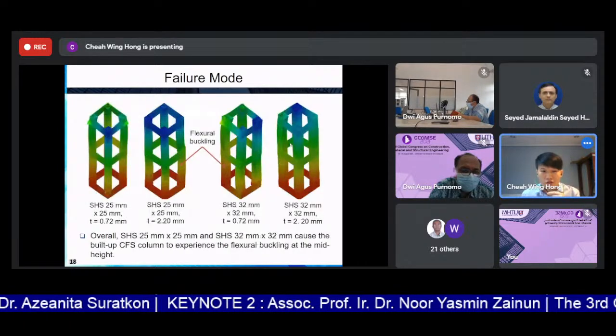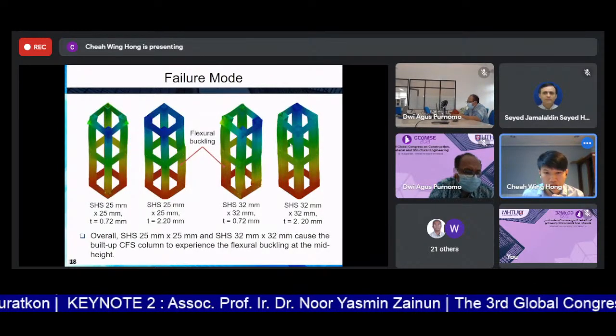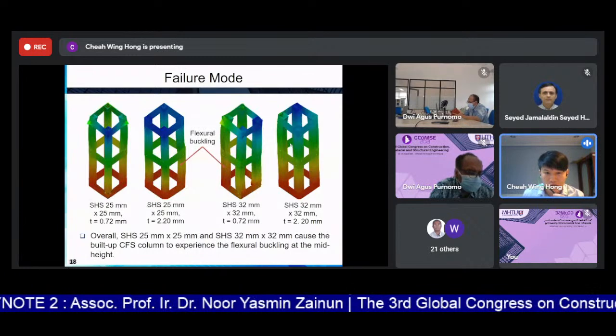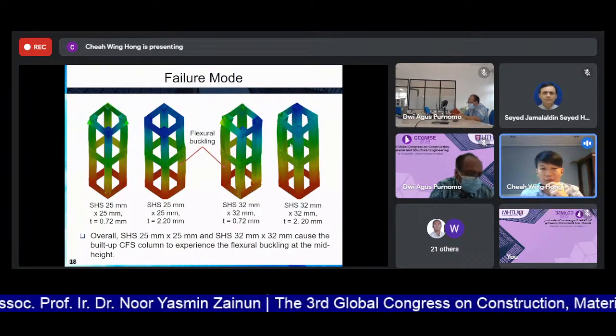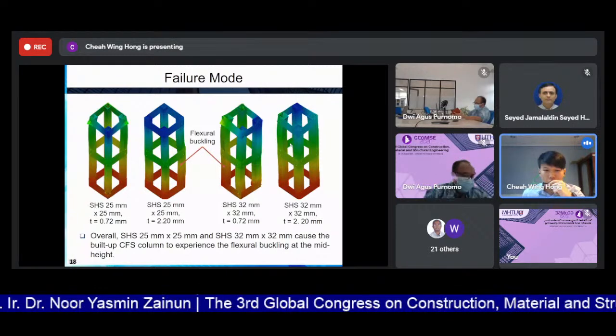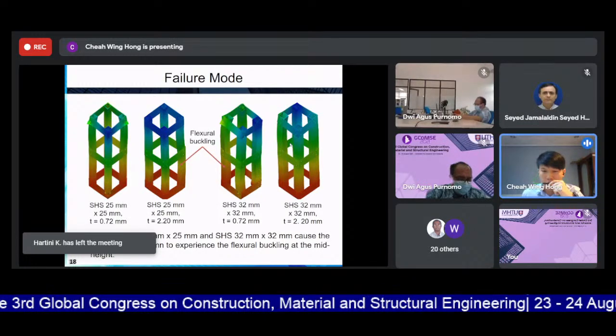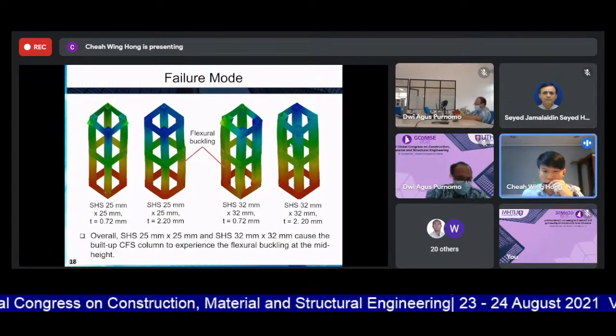So next, these two figures also show the SHS with 25 mm times 25 mm and the SHS with 32 mm times 32 mm. So overall, the SHS of 25 mm times 25 mm and the SHS of 32 mm times 32 mm will cause the build-up CFS column to experience flexural buckling at the mid-height.